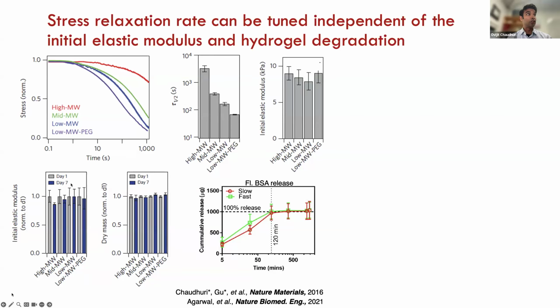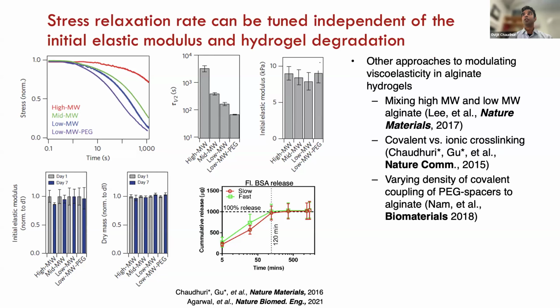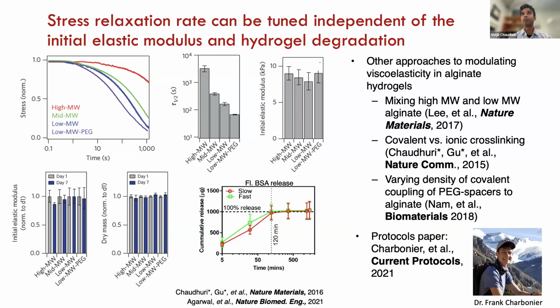Importantly, these hydrogels are relatively stable over 1 to 2 weeks. And if we do fluorescent diffusion studies, we see that the diffusion release kinetics are somewhat similar between these different gel formulations, suggesting at least a similar pore structure. So this isn't the only way to vary viscoelasticity in these hydrogels. We've developed a few other approaches, and we've published a protocols paper, so hopefully it will be useful for anyone who's looking to use these same approaches.